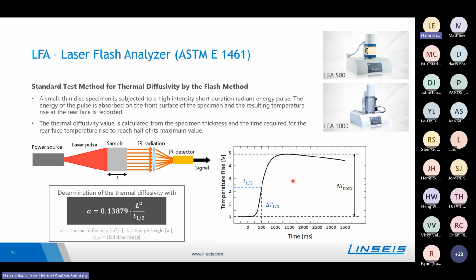A typical signal will look like that. So we have here the temperature rise with time. For the evaluation, the sample thickness is required, as well as the time which is required for the temperature rise to reach half of its maximum value, like it is depicted here. So half of the temperature rise, and we get out the time here. Diffusivity is simplified calculated like that. So we have a factor, and we need the sample thickness as well as this half rise time. So you can already see here that firstly the thermal diffusivity is determined, and if you have information about the specific heat capacity and the density, one can also find out the thermal conductivity in the end.